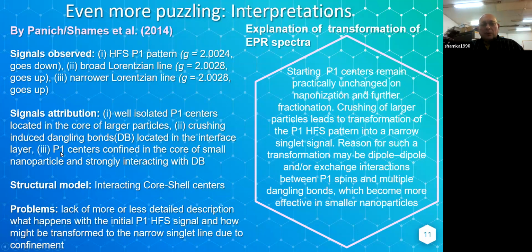This group attributed it to P1 centers confined in the core of small nanoparticles and strongly interacting with dangling bonds.